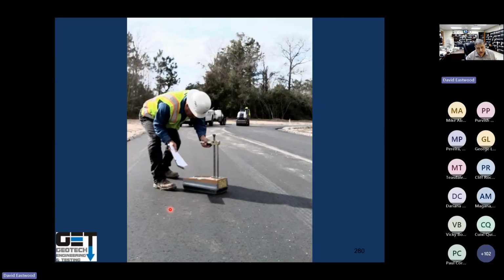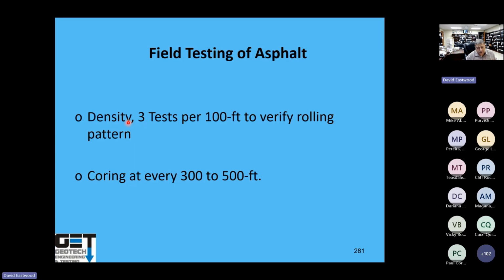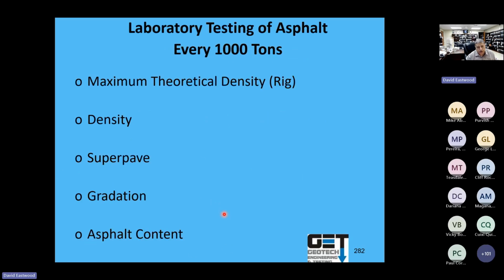Run density tests. Make sure all the densities pass. Usually run 3 densities per every 100 feet to verify the rolling pattern. You core it every 300 to 500 feet. Make sure you got proper thickness of asphalt. We find out we don't have enough asphalt thickness in a lot of projects, so make sure you core it. And you run these tests in the lab: maximum theoretical density, Superpave, gradation, asphalt content.